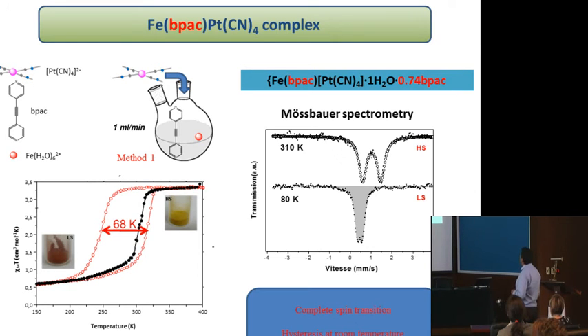Okay, we also use Mossbauer spectrometry to see if the transition is complete or not. Sometimes with magnetic measurement, it's difficult to see if we have a complete transition or not. With Mossbauer, it's very clear. For example, here at 310K, we are in the high spin state, and the spectrum contains only one doublet with a large quadrupole splitting and an isomer shift of 1. This doublet is characteristic of a high spin state. When you decrease the temperature, now at 80K, we are in the low spin state. This doublet disappears, and you have the appearance of this doublet with a small quadrupole splitting, meaning the distance between the two peaks. And this isomer shift of 0.5 is characteristic of a low spin state. So using Mossbauer spectroscopy, we can definitely say that we have a complete spin crossover in this complex. So you have a complete transition and a very nice hysteresis loop centered at room temperature.